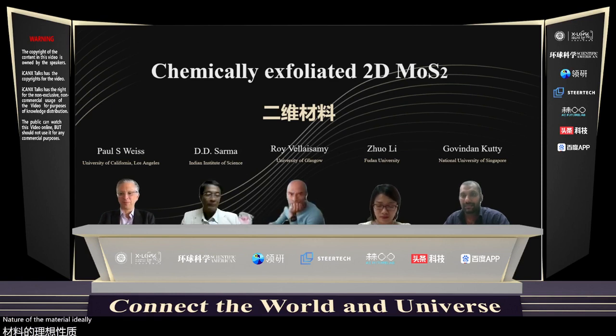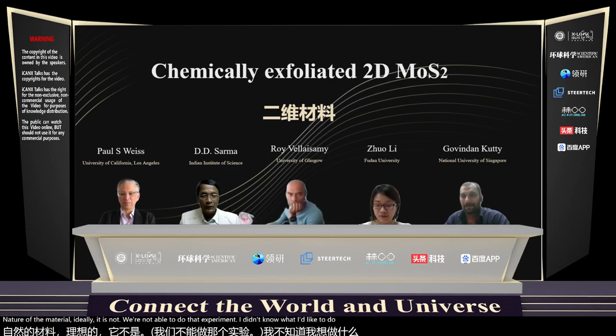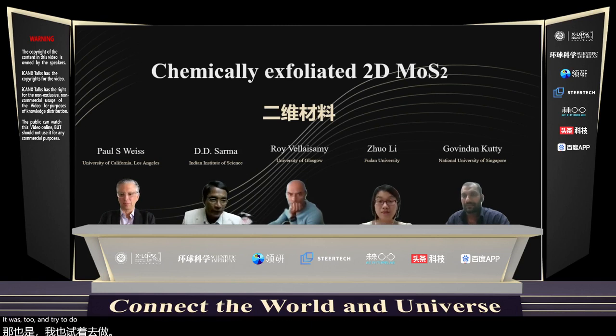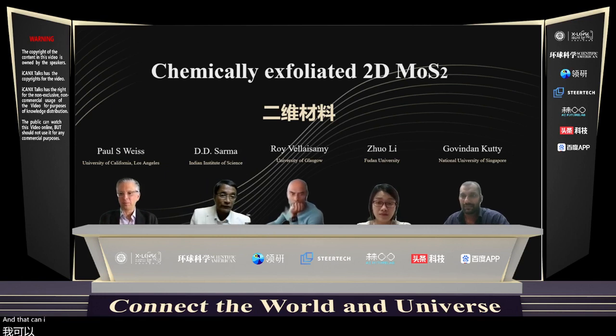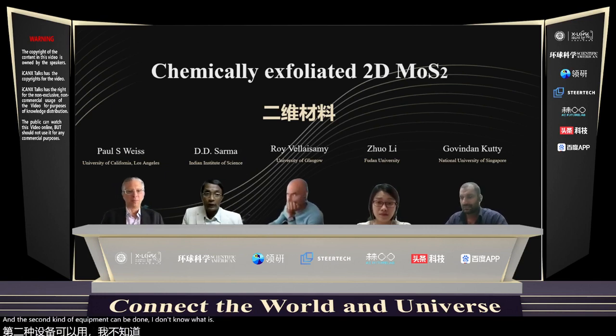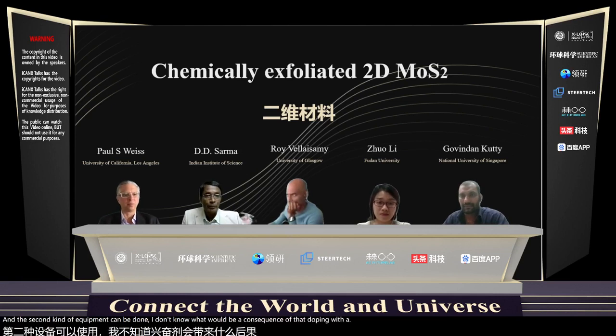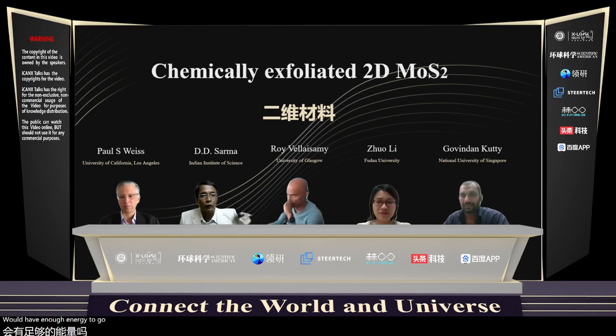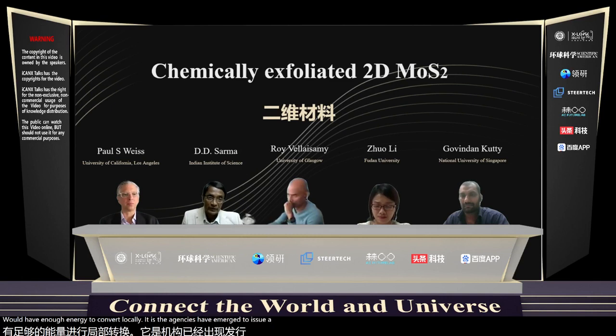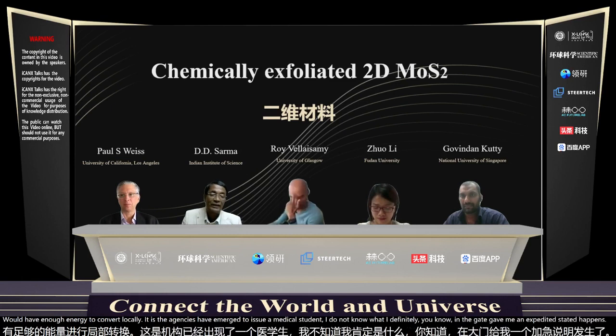Ideally, we are not able to do that experiment. Ideally, what I would like to do is to take a mechanically exfoliated MoS2 and try to dope it by evaporation of lithium in UHV, and that kind of experiment can be done. I don't even know what would be the consequence of that doping, whether it would have enough energy to convert locally the H phase of MoS2 into a metastable state. I do not know. I definitely know in the chemically exfoliated state it happens, but the pathway is very different.